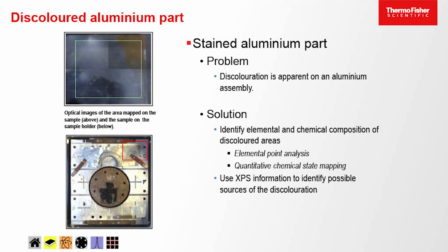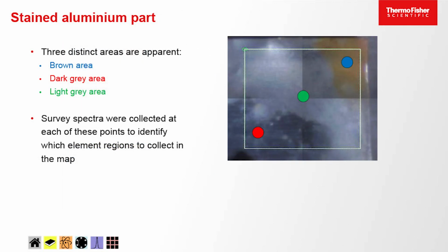and what we want to try and understand is, what's the nature of this contamination, this discoloration in the top corner, and try and establish what maybe is causing the other differences. So you might just be able to see it's a bit lighter here and a bit darker here. See this dark area, light area, and then the brown area up here is the discoloration. So we can easily, optically see these three areas. This looks a bit like a patchwork because it's actually quite a bit larger than the field of view, so the software has just tiled together images for our area.